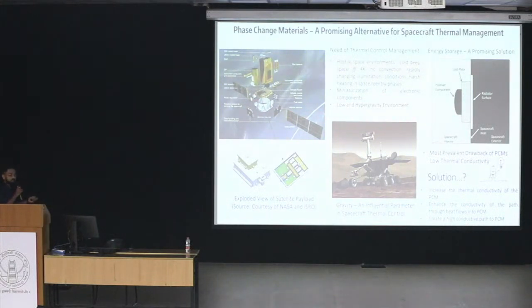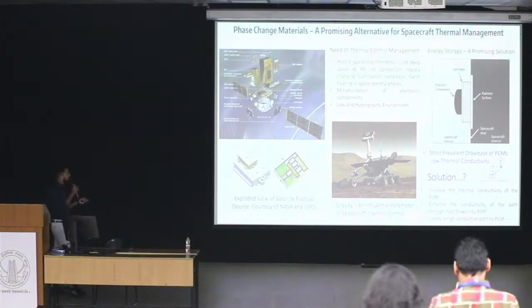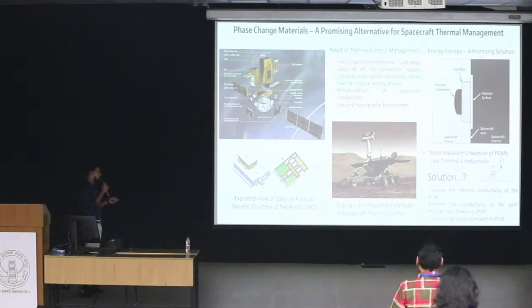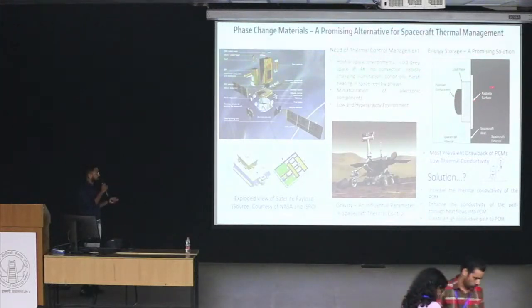So, accounting all of these challenges, we need to design a system that can work efficiently. For that, phase change materials, the latent heat energy storage based materials, can store the energy during the on period in the satellite payload, and reject the heat during the off period in the satellites. So the baseline condition is that, let's say I have shown here the payload component, the electronic component, and this is the radiator surface which is exposed to the space exterior, which is at 4 Kelvin temperature.